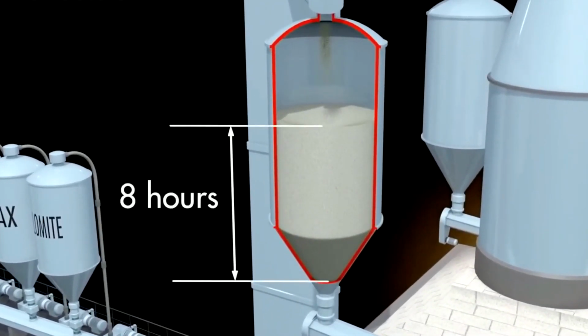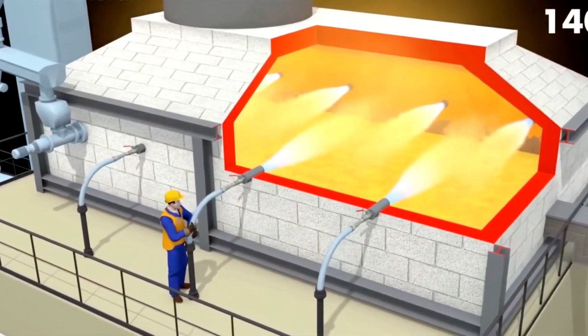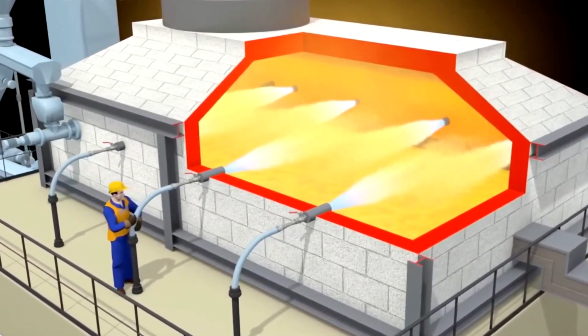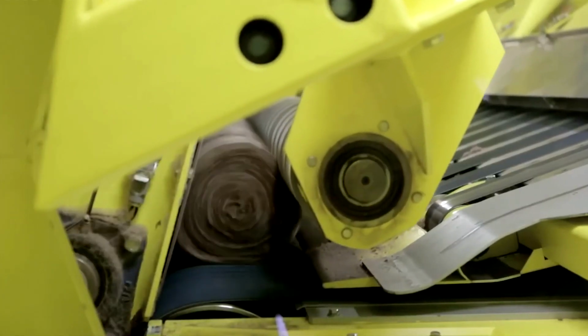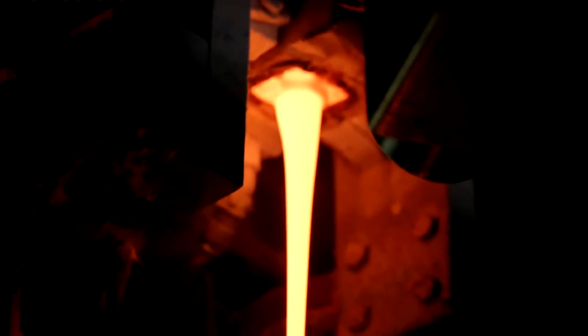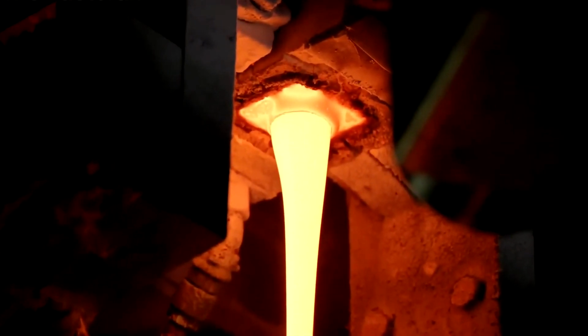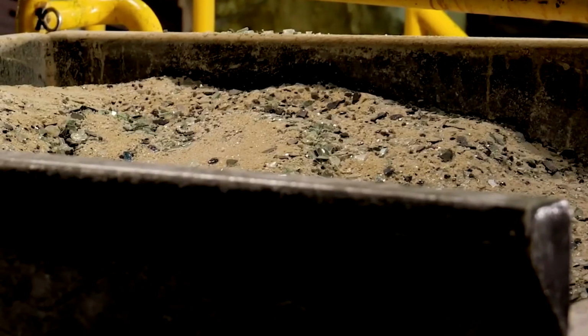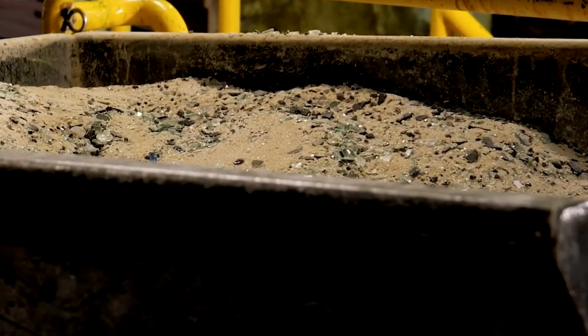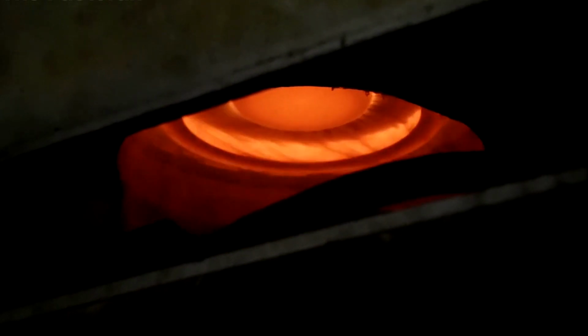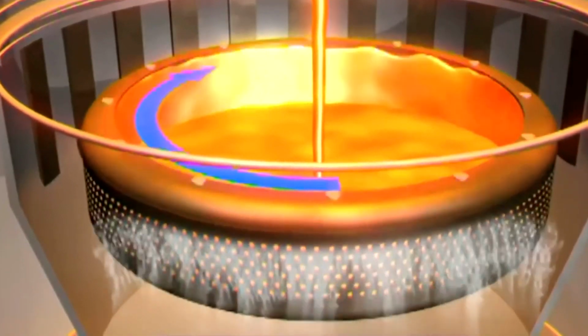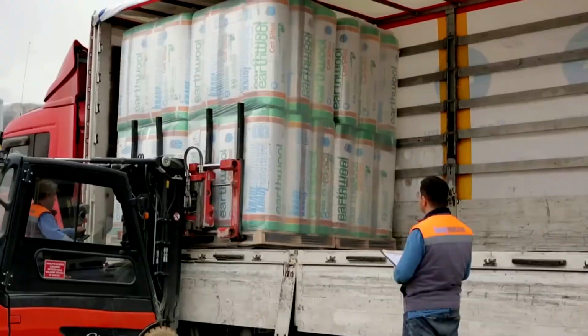The materials are fed through a water-cooled screw conveyor into the massive chamber, which combines gas-oxygen firing with supplemental electric resistance to deliver both power and environmental efficiency. Inside, molten glass boils at around 1400 degrees Celsius, with flames sweeping across the surface, while electrodes remain submerged beneath the melt. From here, the glass streams through heated channels that maintain the exact viscosity needed before it can be spun into fibers. The molten glass flows into a spinner rotating at an extremely high speed, shooting out through thousands of tiny holes to form a cascade of ultrafine fibers.